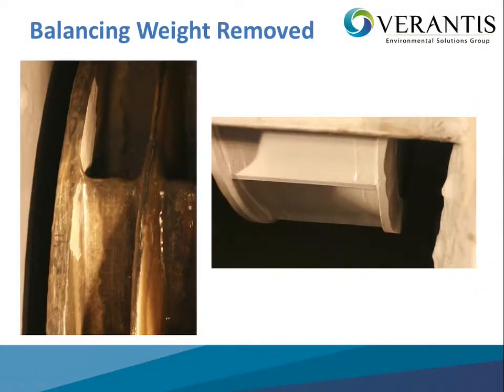Now, this is what happens when you remove weight. And like I said, we don't ever remove weight. We only add weight for balancing. The impeller on the left, they actually ground the inside of the impeller in order to balance it. And then they neglected to re-top coat it. So what you're looking at, those white spots right there, are actually exposed fibers, which are going to be prone to chemical attack.